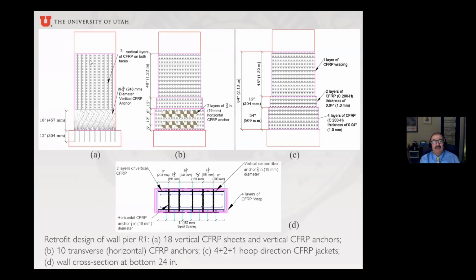The other thing we did before we put these anchors, we put vertical sheets to take tension in this direction, because as I told you, the steel in this direction was actually very small reinforcement ratio. And we also found that if you sandwich these anchors with 2 layers of sheets, they actually perform very well. In addition, to improve the shear friction capacity of the lap splice, we use horizontal anchors through the 12-inch thickness.